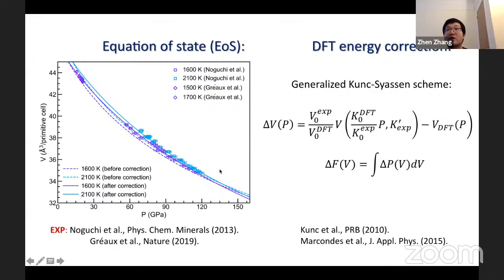For practical applications for geoscientists, the energy correction was made to the reference DFT energy with reference to the experimental data to bring the calculated equation of state into full agreement with the experimentally measured ones. The generalized Kunc-Syassen scheme was used. The corrected equation of state agrees very well with the experiments. Once the correction is done at experimental temperature, the same energy correction was applied to other temperatures in our calculations.